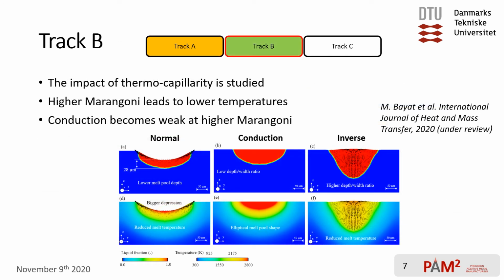In the second investigation track, as I noted earlier, I studied the impact of thermocapillarity, or the Marangoni effect, on the melt pool conditions. We found that by using higher Marangoni numbers, we will have lower melt pool temperatures. That in turn will reduce the significance of conduction inside the melt pool as we destroy the temperature gradients during the process. This work is currently under review in the International Journal of Heat and Mass Transfer and hopefully will be published soon.